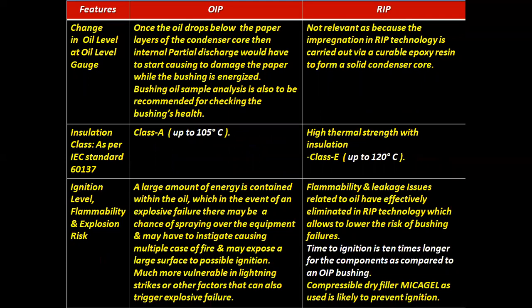Change in oil level at the oil level gauge. Once the oil drops below the paper layers of the condenser core, internal partial discharge will start, causing damage to the paper while the bushing is energized. Bushing oil sample analysis is also recommended for checking the bushing's health.